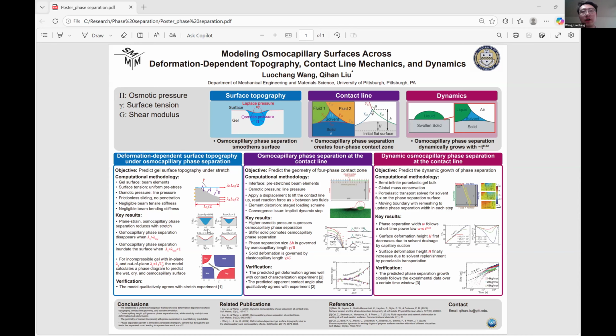And osmotic pressure is modeled as a line pressure. And we apply frictionless sliding, no penetration as our contact. We find that in the plane strain case, phase separation reduces with stretch and the surface becomes smoother. This means the solvent actually gets absorbed inside the gel's bulk. And the phase separation can disappear under large stretch.